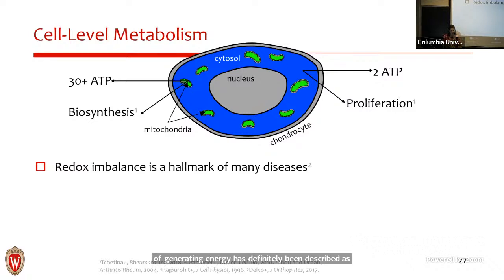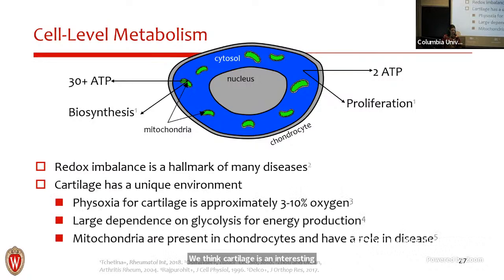Now, we think cartilage is an interesting case to look at this idea of redox imbalance, in part because it has such a unique environment. In the mature animal, there are no blood vessels in the cartilage, so the oxygen concentration is relatively low. People have estimated this as roughly 3 to 10%, so that's certainly below the 21% oxygen that most rooms are at. So this has meant that cartilage has a relatively high dependence on glycolysis for normal function, for energy production.